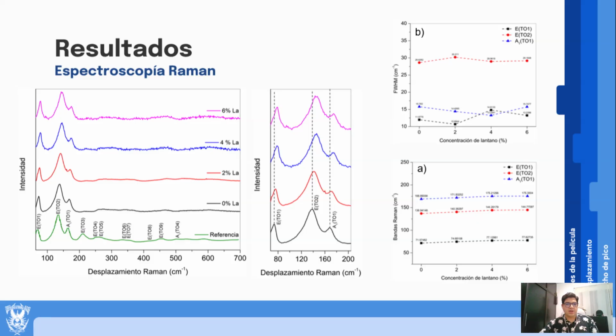Raman spectroscopy confirmed phase purity in lanthanum-doped BFO while revealing dopant-driven structural changes. Peak shifts and intensity variations indicated lattice modifications, particularly in bismuth and oxygen bonds. At 6% of lanthanum, peak broadening signaled increased structural disorder. Full width at half-maximum analysis quantified these distortions, linked to improved material stability and reduced impurities. These modifications are critical for enhancing BFO's optoelectronic performance in thin-film devices.